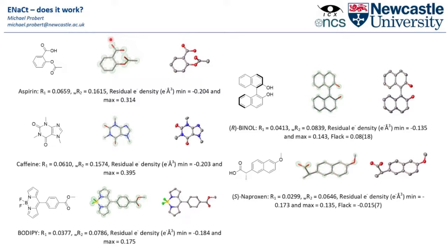So these are FOBS maps. So this is the electron density that is seen for our structures, getting very, very good localization of density. So the crystal quality is very high, and then a final refined structure on the side with all the hydrogens taken out. And you can see even resolution of the stereochemistry via the Flack parameter is very good. So this generally works. So does it work on this subset of compounds? Absolutely, although this subset of compounds was stacked in our favor.